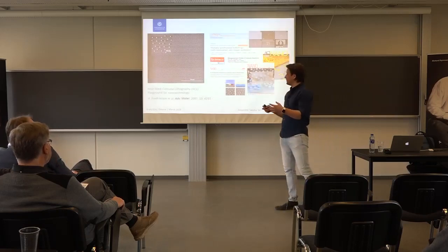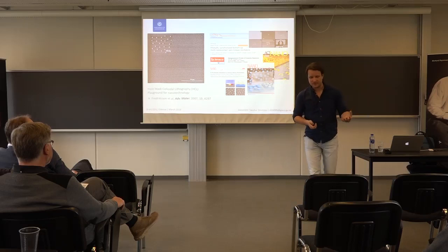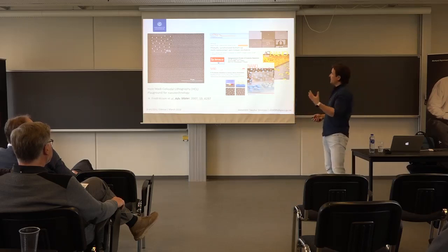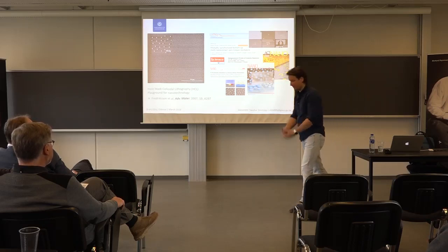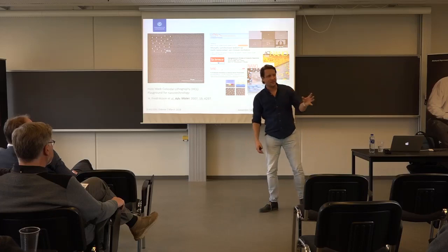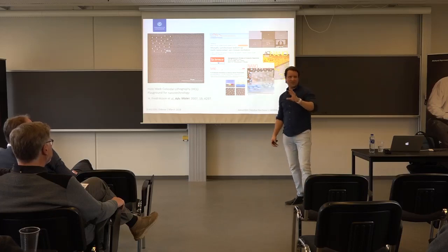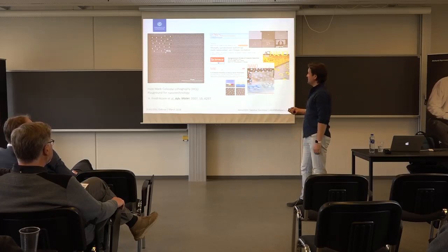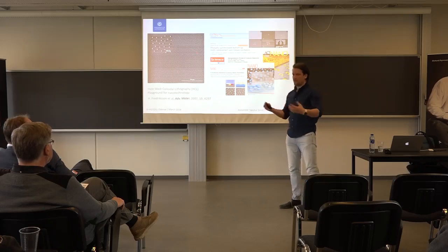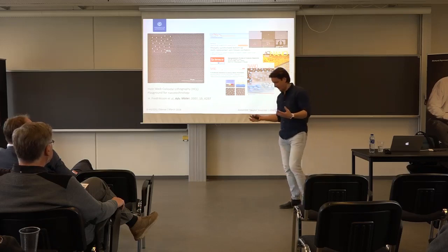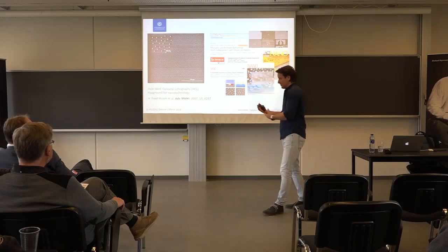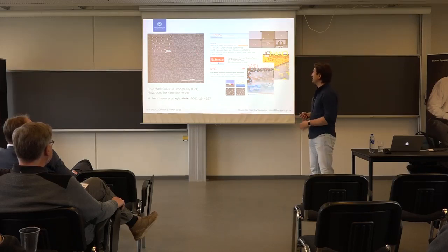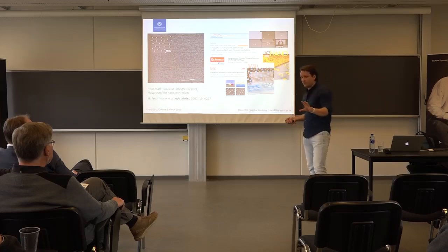But since I mentioned the nanostructures, and since I mentioned that we like them so much, I can briefly tell you how we make them. So it so happens that back in Gothenburg, where I work, we have a tradition of developing bottom-up nanofabrication methods. Bottom-up means we let nature do the job by itself. When we fabricate something, we just allow the structures to assemble in a particular pattern that is governed by electrostatic forces and interaction with the substrate, so there are different parameters that enter. And then we use that as a mask to create all sorts of nanostructures.